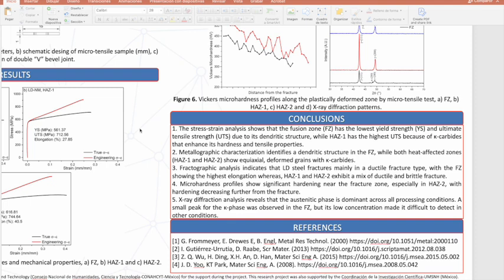Conclusion 3. Fractographic analysis indicates that low-density steel fractures mainly in a ductile fracture type, with the fusion zone showing the highest elongation, whereas HAZ1 and HAZ2 exhibit a mix of ductile and brittle fracture. Conclusion 4. Microhardness profiles show a significant hardening near the fracture zone, especially in HAZ2, with hardening decreasing further from the fracture. Conclusion 5. X-ray diffraction analysis reveals that the austenitic phase is dominant across all processing conditions. A small peak for the κ phase was observed in the fusion zone, but its low concentration made it difficult to detect in other conditions.